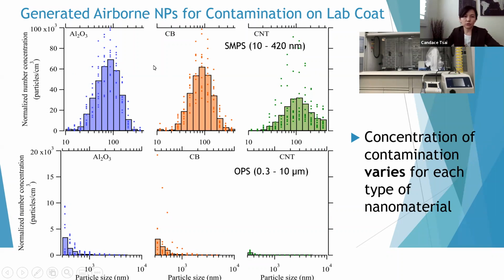The graph shows the top layer here is particles below 420 nanometers. You can see a lot of particles are pretty small, around 100 nanometers, with slightly different distributions among the three different nanoparticles, and most of them are small. For concentration less than 10 micrometers, we found carbon nanotube has very low concentration in this range. However, we concluded that carbon nanotube actually has a lot of agglomerate, and the agglomerate of carbon nanotube is actually beyond 10 micrometers. We don't have an instrument above 10 micrometers, but we found that they are huge.